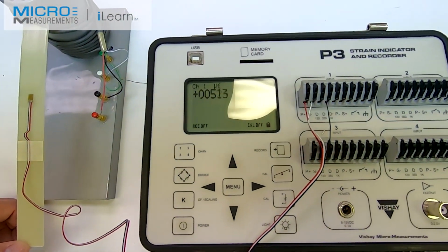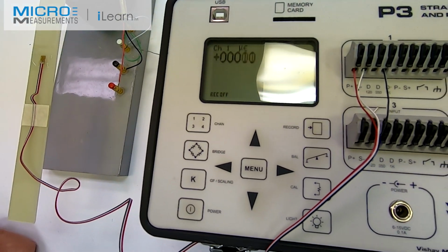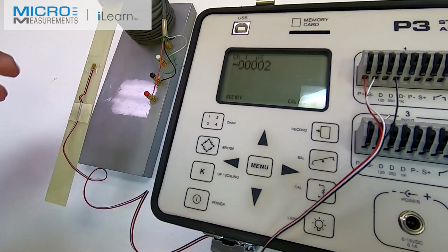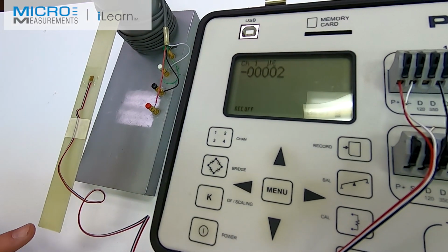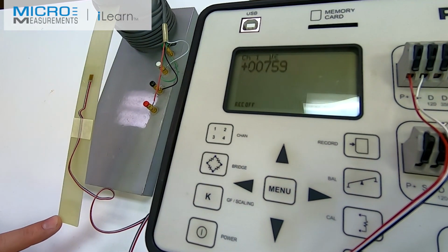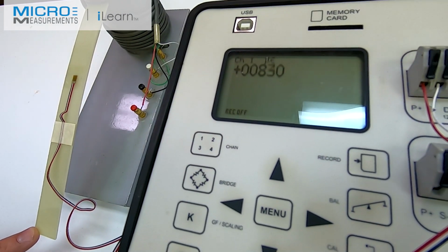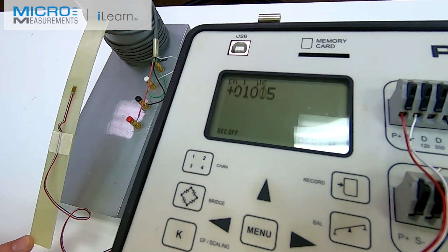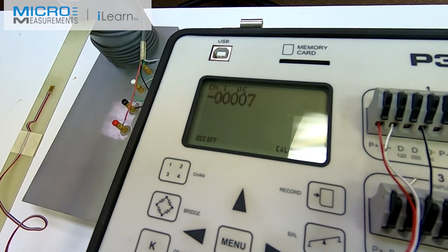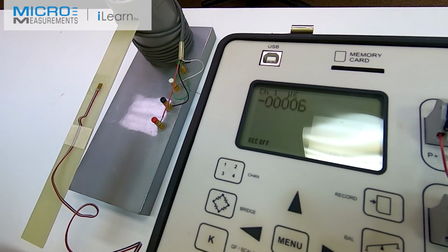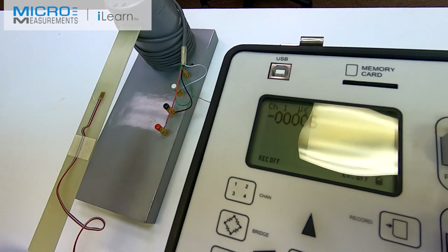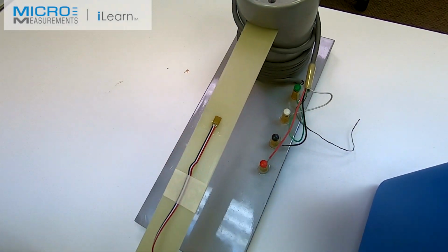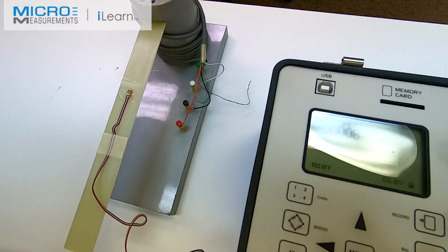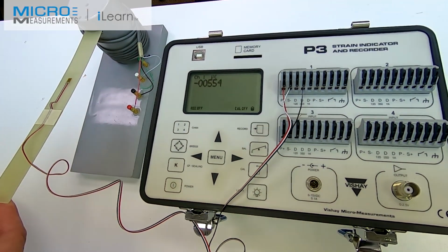So as I bend it down, you can see I'm loading it in tension, and I let it go. And not bad. It's coming back within 1 or 2 microstrains, pretty good for a fiberglass composite beam. Here I go to 700, 800, pushing up around 1,000 microstrain, and then I let it go. And letting it go, you can see that we've got a few counts of initial offset. And those few counts typically are associated with the material properties of fiberglass. It's not going to respond as well as a high strength grade of steel or maybe an aircraft grade of aluminum alloy, just because it is a composite material.